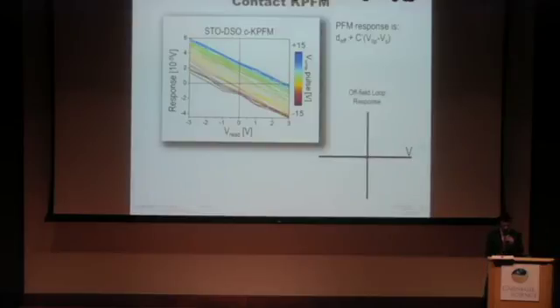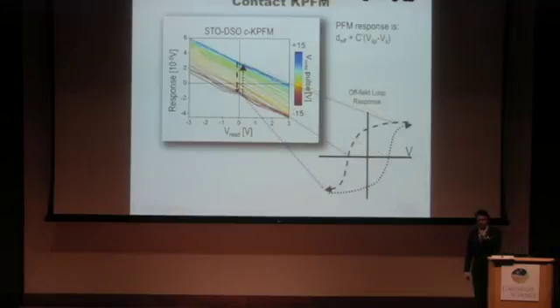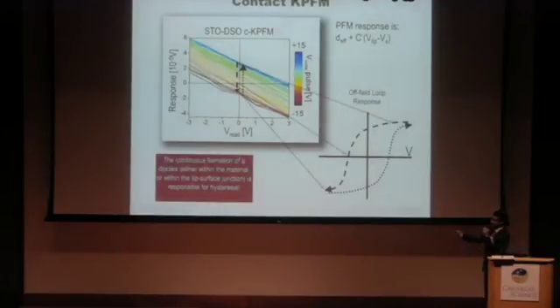Why is this important? Well, if you look along this particular axis here, you will see some bunching, right? You see some lines bunching here and some lines bunching here. And so even from a purely electrostatic response, you see this kind of hysteresis loop that occurs. This is interesting and also kind of disheartening in a way, because it means that if you see this ferroelectric hysteresis loop in PFM, it doesn't mean that you have a ferroelectric material. Nonetheless, the important part here is that I want to give you an idea of how to read these particular diagrams. We also think that the reason you see this bunching is because you're creating some dipoles, for example, either within the material or within the tip-surface junction, and that's actually responsible for this type of hysteresis.